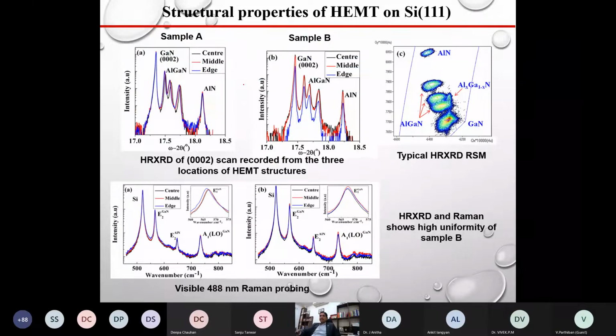Again, by HRXRD we see these layers are highly C oriented; the gallium nitride orientation is C. Again, we can measure how much stress is there. Almost all of this stress is relaxed. Only the initial aluminum gallium nitride layers have stress, while the top layer, our gallium nitride, is almost stress free. So by managing different layers, we can grow almost stress free layers, and stress free layers mean a very small number of defects.